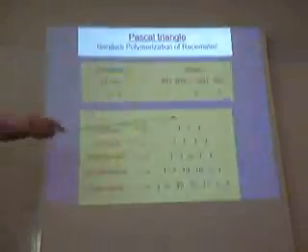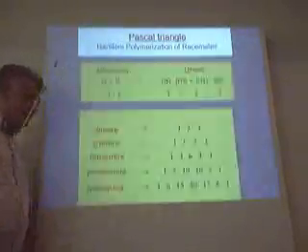If you take a racemic mixture of two components, and go to the first one, you take dimers, which are RR, RS, SR, SS, whereas the wings of this represent the homochiral peptides. And this also demonstrates that if you go to very long peptides, the wings become smaller and smaller. So there must be some mechanism by which one can convert the polymerization of racemic mixtures into polymers of homochiral sequence in this system.